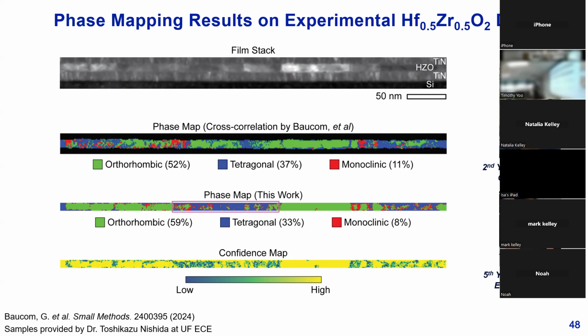And so comparing that to the phase map from this work, we can see that first the phase volume fractions between all three phases, between the two different outputs here, are fairly similar and in pretty good agreement with each other. However, the main differences between the two outputs mainly reside within the actual spatial layout of where the phases are being located, particularly in regions like this purple box. In order to get a better idea of why this might be, we can take a look at this confidence map on the bottom. It's basically a quantitative measurement of how sure the model is of its initial top output versus the second output. And we can see that, especially in regions like this purple box here, the average confidence value in this region is fairly low, this sort of dark blue green region, versus regions that are high in confidence, like in yellow, that seem to match up well between both this work using machine learning and prior work using cross-correlation.